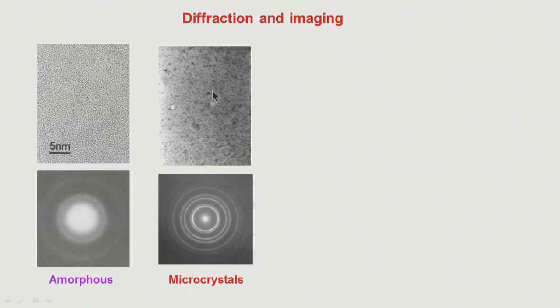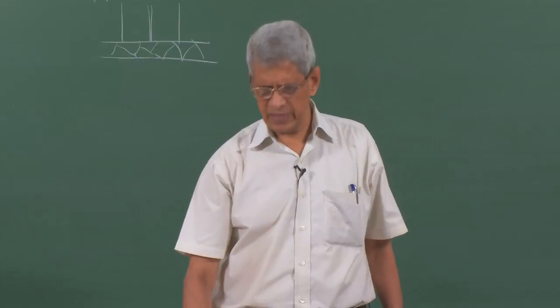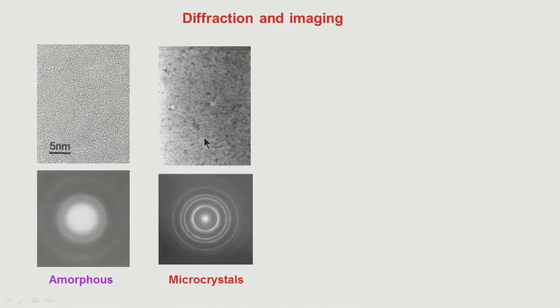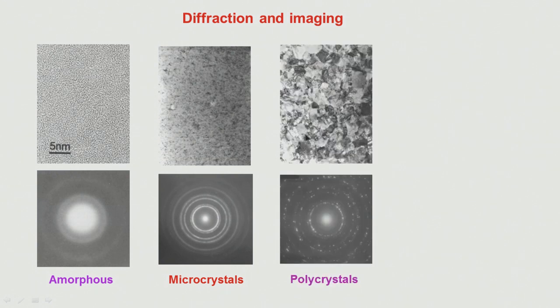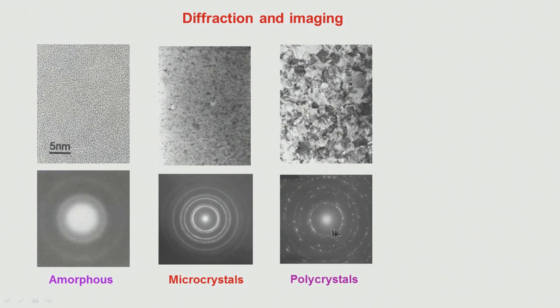Samples with very fine grain size, where grains are all randomly oriented, give a circular ring pattern in diffraction. This applies to nanocrystals in the range of 10 to 100 nanometers. If the particle size is slightly larger — in the micrometer range — depending on the aperture size and orientation of the various crystals, if totally random we should get a ring pattern; otherwise we get spots on specific rings. These rings can also be analysed to get information about crystal structures.